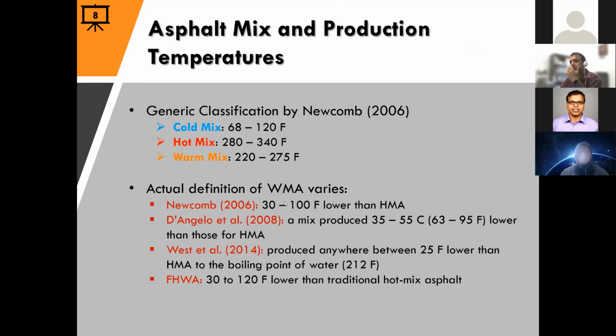First of all, this is a webinar on warm mix asphalt, and the interesting thing is that there is not one single definition of what warm mix asphalt is. Newcomb in 2006 presented a generic classification, with 68 to 120 Fahrenheit, 280 to 340 Fahrenheit, and then 220 to 275 Fahrenheit. So basically warm mix asphalt was 220 to 275 Fahrenheit. But then there are other definitions as well.